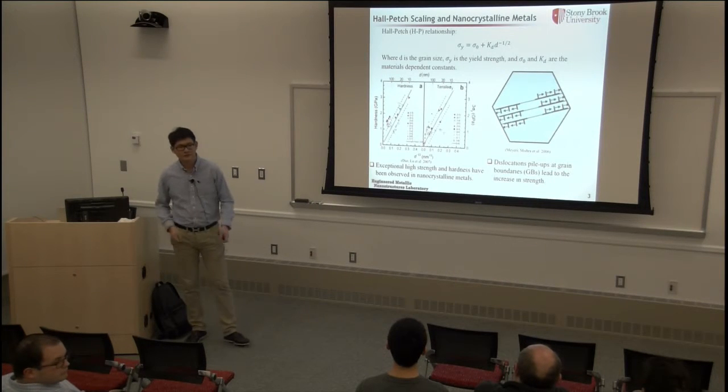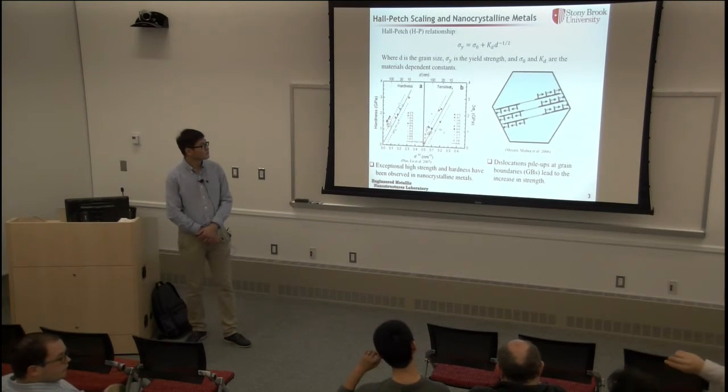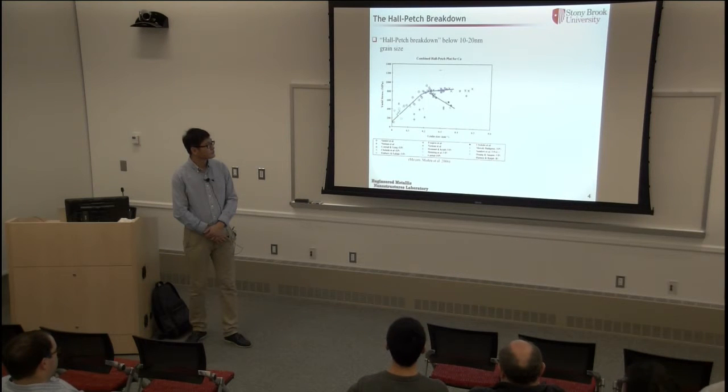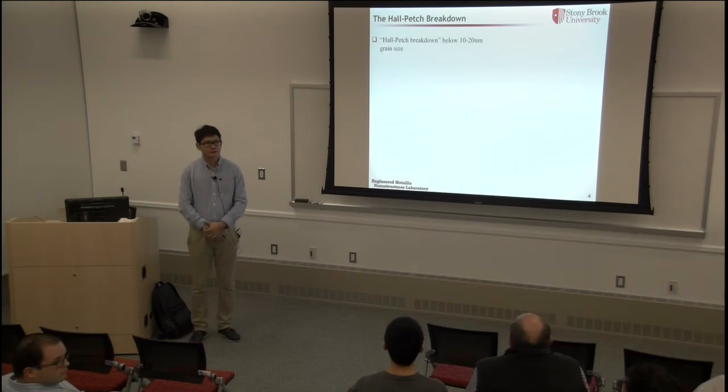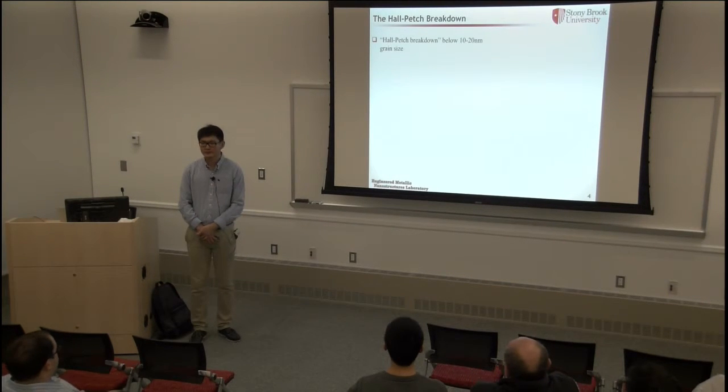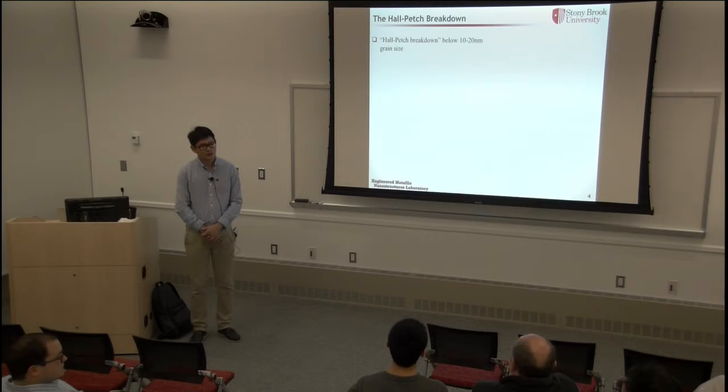So, for example, dislocation nucleation at grain boundaries, which is not found in classical Hall-Petch but is found in nanocrystalline metals, where you start to come up to this plateau of Hall-Petch strengthening. That's because the fundamental dislocation mechanisms shift to grain boundary mediated processes versus the classical dislocation interaction type mechanisms. But the conclusions would definitely depend on temperature.